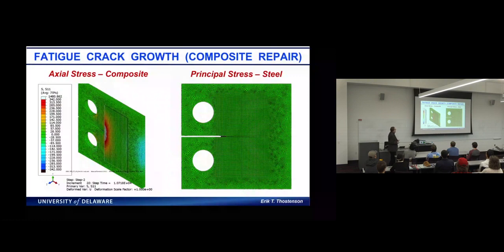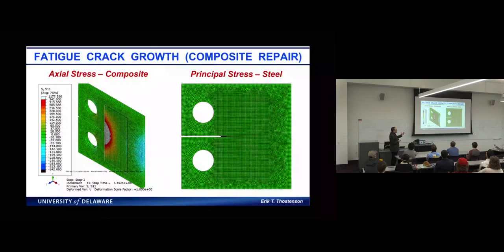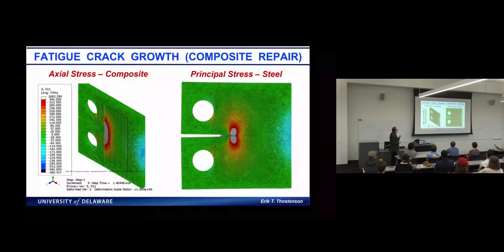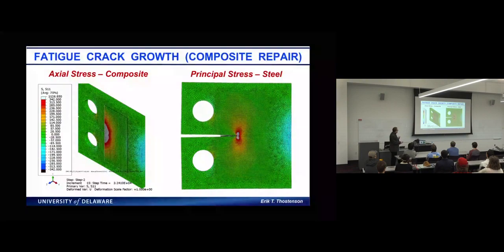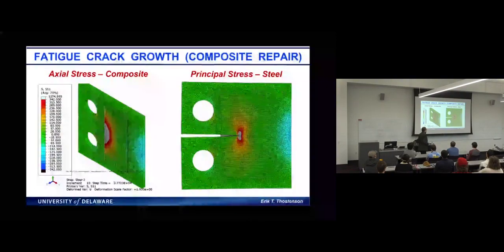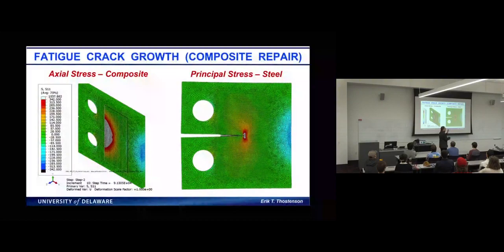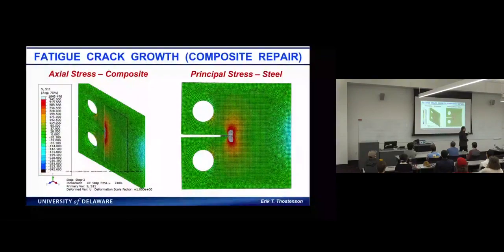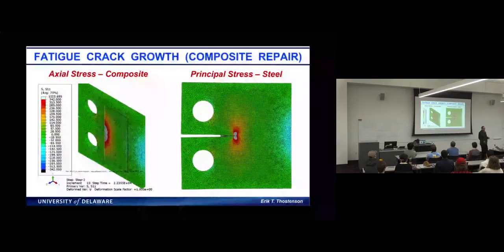This is just an example of now the stress that's in the composite with the composite repair. And you can see as that crack grows, that carries more. But as that crack continues to go, actually the stress concentration decreases. And that's because the composite is carrying more stress. So we matched the Young's modulus of the composite to really optimize that.